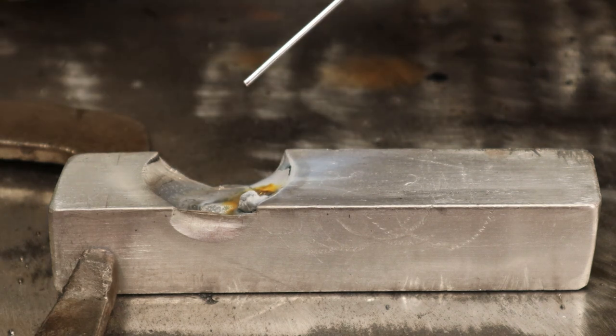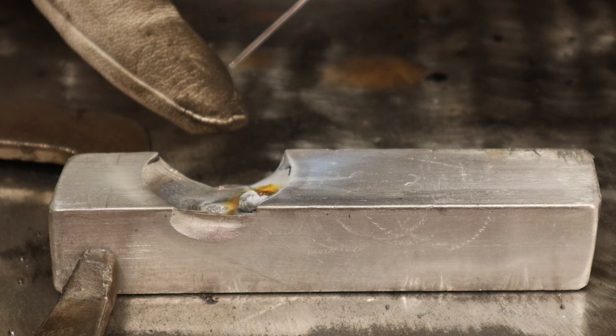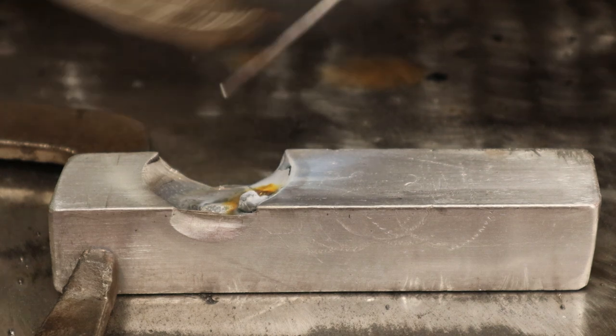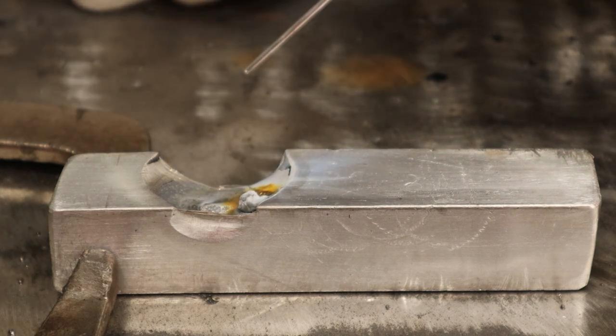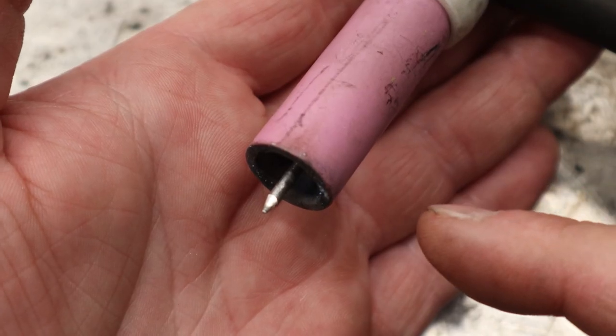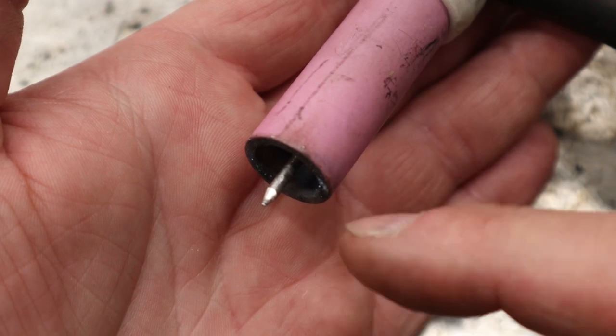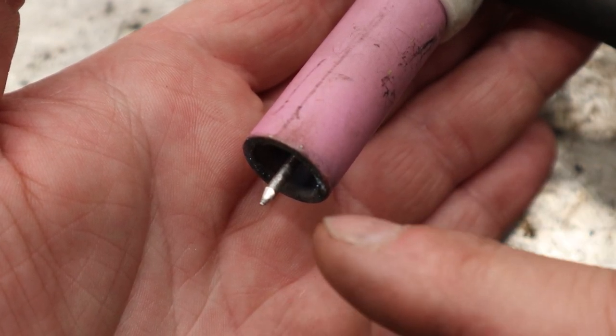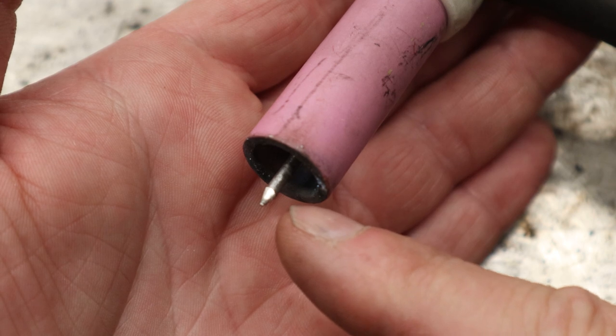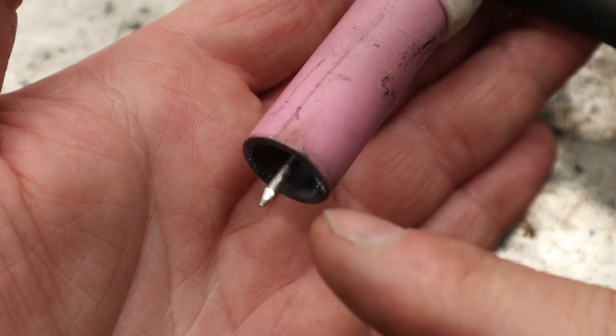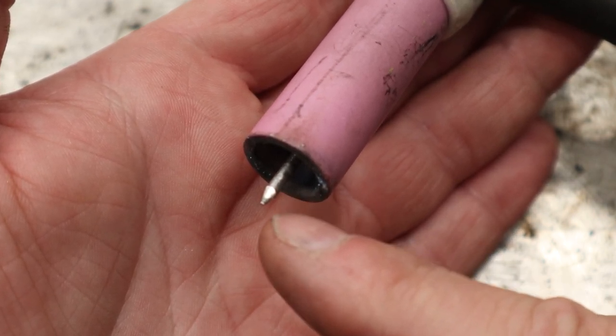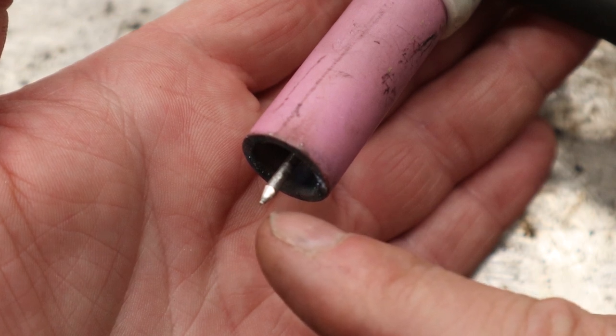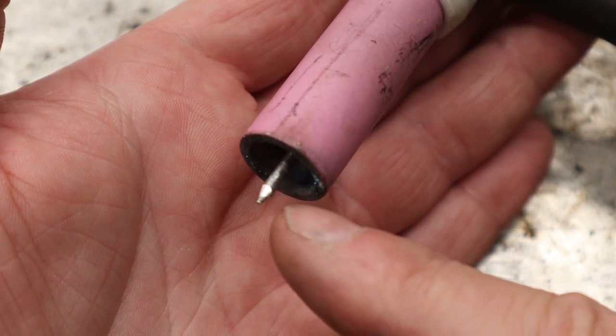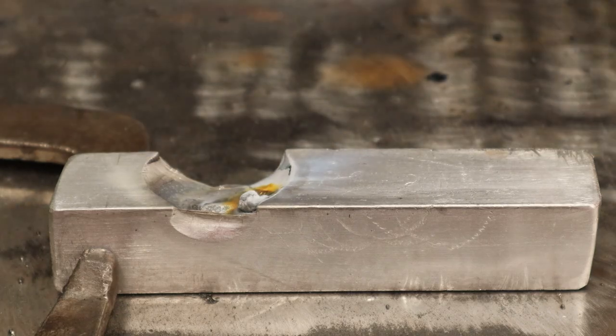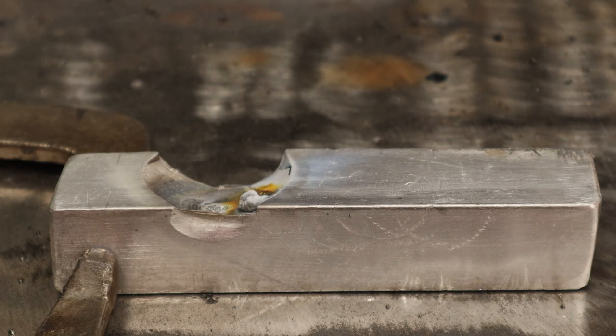So the good thing is we can put a lot of heat into the material. However, there is zero cleaning action happening here and the oxides are not coming off, so we can't penetrate it, we can't weld. It's something to note with this DC negative setting, you are putting all of the heat down into the material, and that means there's actually kind of a cooling action happening on the tungsten electrode. Because of that, if you take a look, there's still a blunted, sharpened point there, and there's no balling happening because that electrode is just not getting hot enough. So that was DC negative. Let's flip it to DC positive and see what happens there.